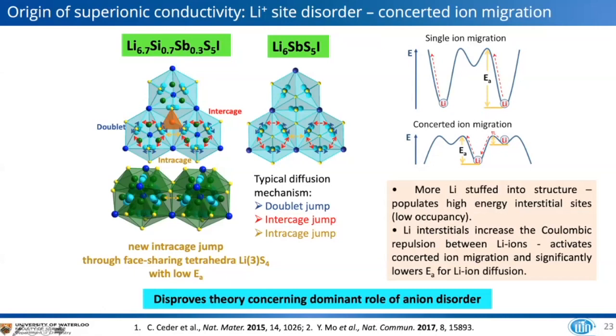And so this allows a concerted ion migration path to take place because we populated effectively these high energy interstitial sites. And this activates a concerted ion migration, which was reported by Yifei Mo, also by Gerbrand Ceder, and lowers this activation energy for lithium ion diffusion.